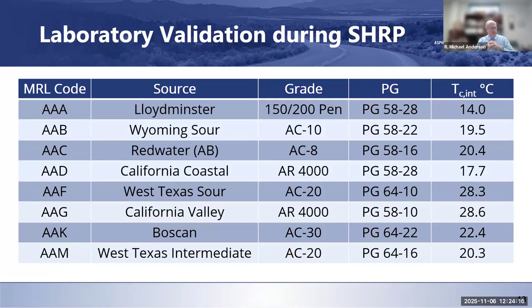These were the asphalt binders that you see there. These are the references, different grades. They had different intermediate temperatures. But all the testing that they were doing for flexural beam fatigue was at 20 degrees C. So even though they all had different performances, at 20 degrees C they were all going to look a little bit different in terms of their G star times sine delta value and their relative stiffness. So if you just looked at it that way and at the intermediate temperatures, binder AAA would be the softest overall because it had the lowest intermediate temperature. AAF and AAG would be the hardest, or the stiffest, because they would be expected to have the highest value overall.